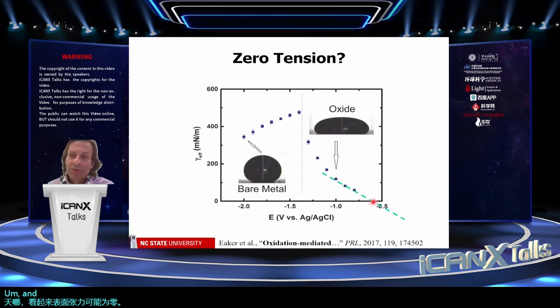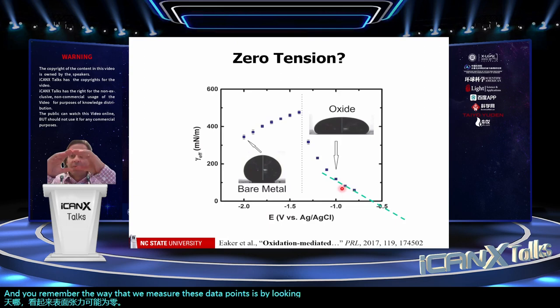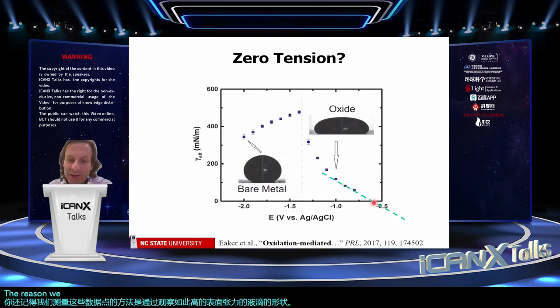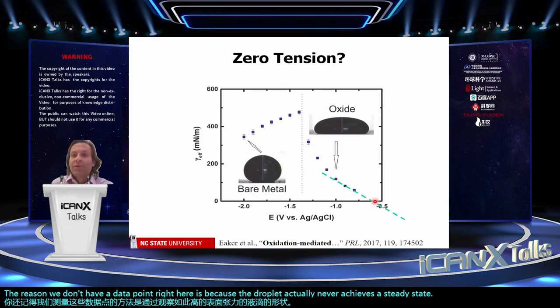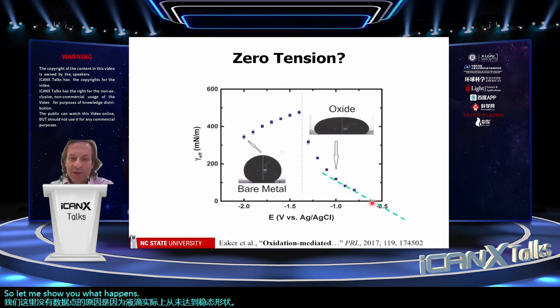And you remember the way that we measure these data points is by looking at the shape of the drop. So high surface tension, low surface tension. The reason we don't have a data point right here is because the droplet actually never achieves a steady state shape. So let me show you what happens if you apply this voltage right here.